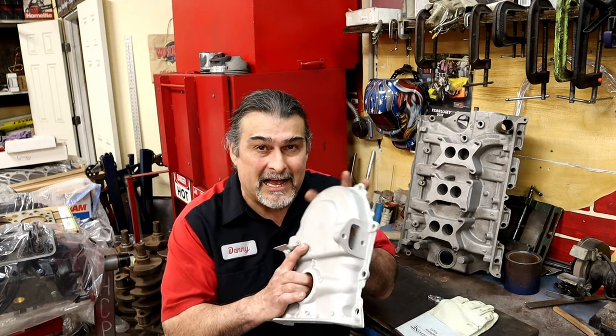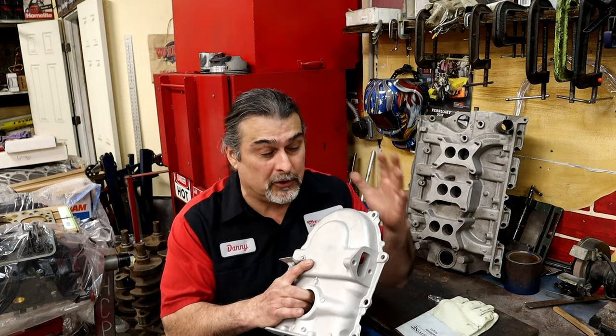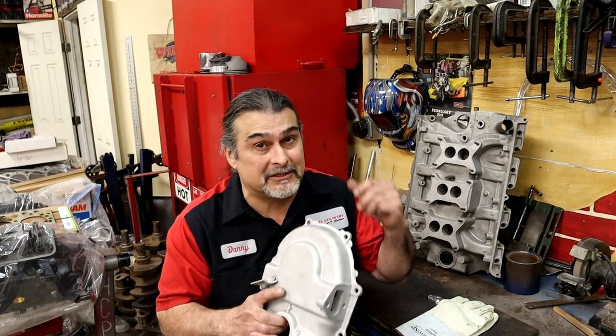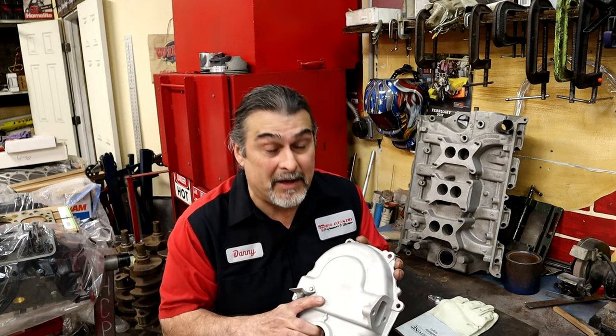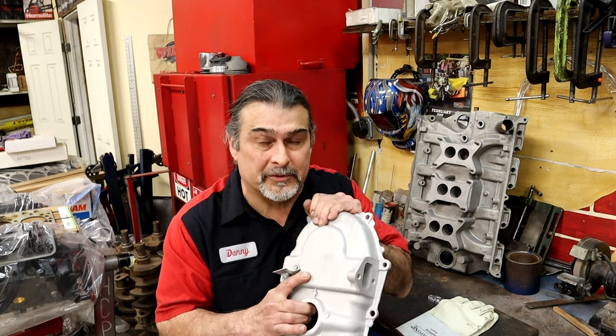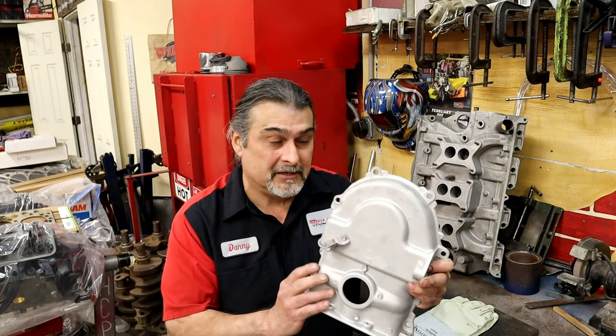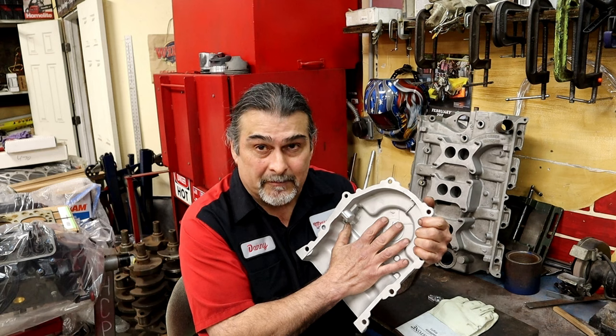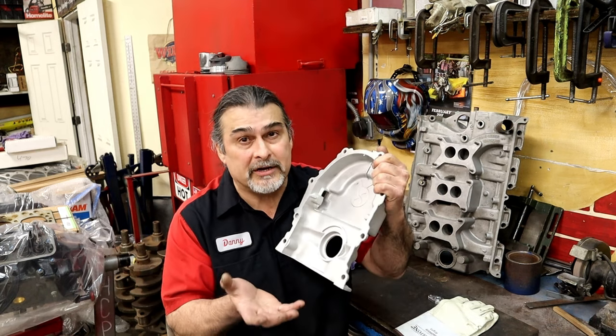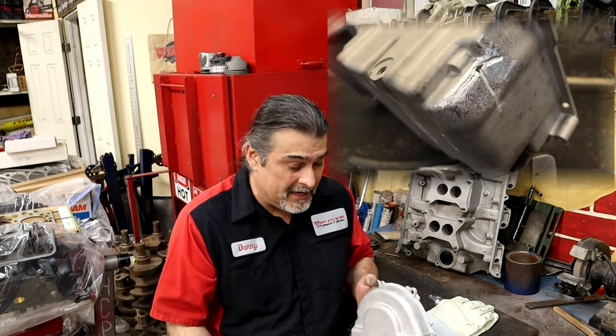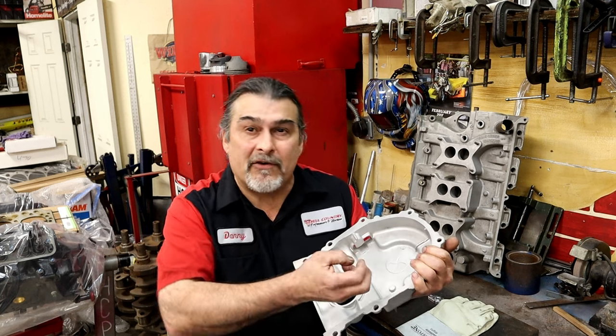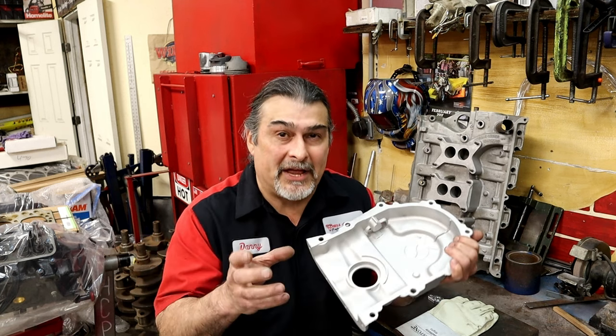The first thing is cast aluminum is real porous. The older the parts, Harley Davidson stuff, Jaguar stuff, really bad. It's a cast piece of aluminum. As it heats up, it expands. The inside has oil in it. An oil pan is one of the hardest to weld, and I'm going to show you an example of an LS oil pan that had some cracks in it and how I repaired that. But cast aluminum expands, oil gets into it, and that's why when you go to weld, you have all these contaminants coming out, and that's the difficulty.